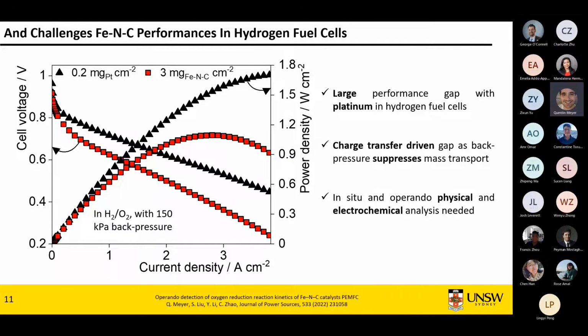So this is the performance we get of our catalyst in fuel cell. This, in red, is a fairly decent PGM-free catalyst. We get about 1.1 watts per centimeter square, which places us in the top range of materials. When we compare it with platinum, we still have quite a way to go. Platinum gives you about 1.8 watts per centimeter square. If you even look at fully commercial fuel cells, you typically get somewhere around 2.4, 2.5 watts per centimeter square. So we still have a large way to go for material.